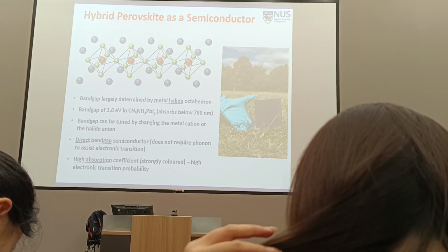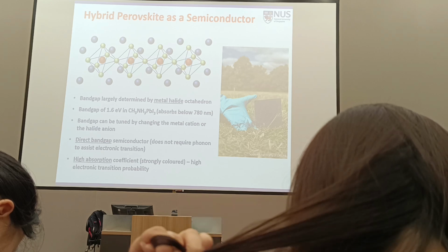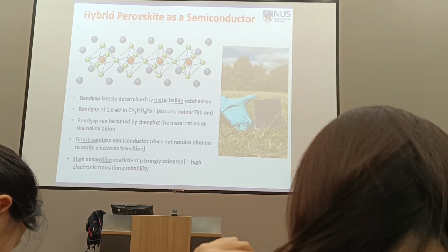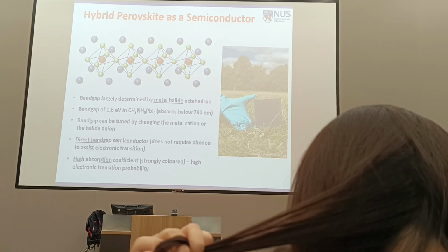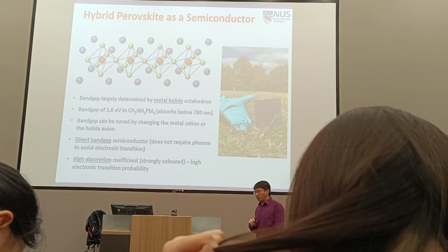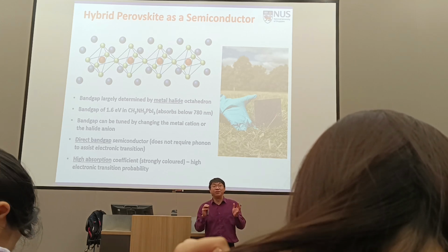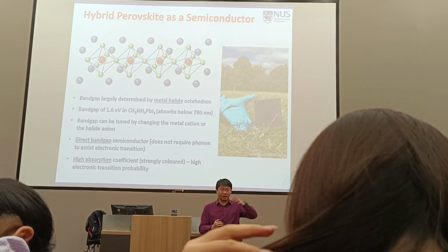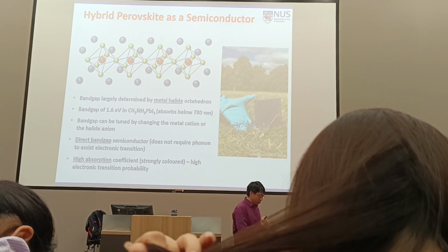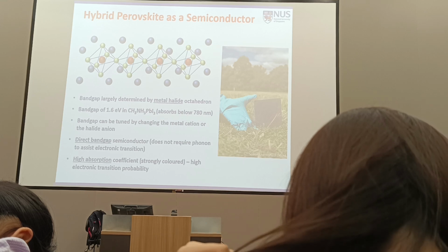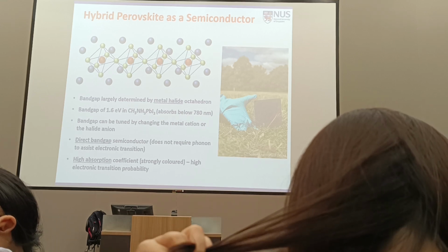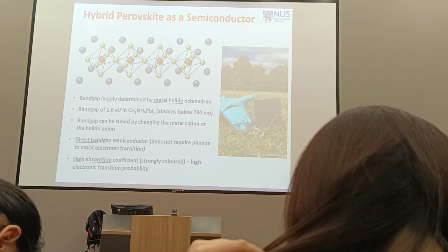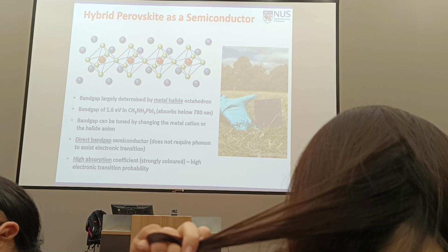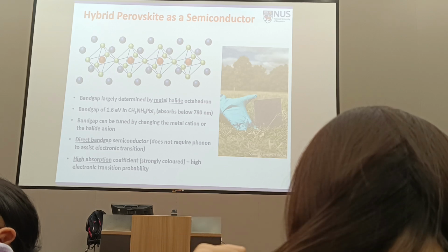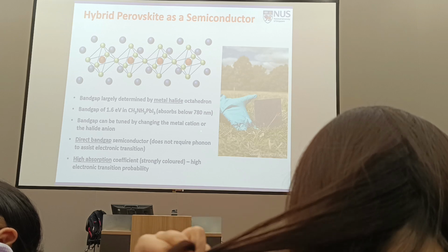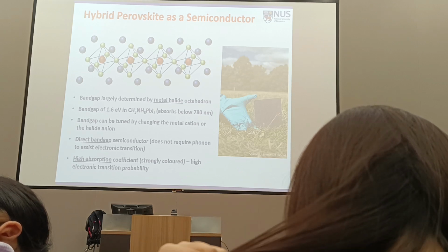Now, the perovskite that became popular for solar cells has a band gap of 1.6 electron volts. If you do a calculation, this allows the perovskite to absorb a lot of light in the visible spectrum. This is why it's a good solar cell, since sunlight has a lot of visible spectrum. It absorbs below 780 nanometers, basically. And as I've mentioned, and we have gone through in the question, I can tune the band gap by changing the metal or the halide anion.